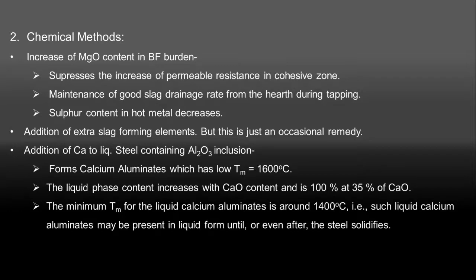We can increase magnesia content in BF burden. It is helpful as it suppresses the increase of permeable resistance in cohesive zone. Magnesia helps in maintaining good slag drainage rate. It also decreases sulfur content in hot metal. Addition of extra slag forming elements dilute the concentration of alumina in slag, but this is just an occasional remedy because if we keep on adding slag forming elements, slag volume increases but productivity decreases.